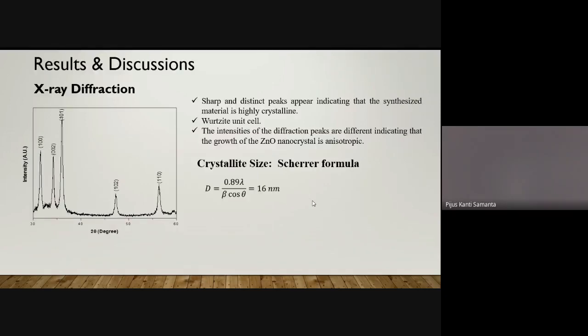The structural studies involved X-ray diffraction studies, and here it shows the X-ray diffraction pattern of the synthesized material. Sharp peaks appeared over here that indicate the good crystallinity of the material, and we have indexed these peaks and found the structure to be hexagonal, and this peak indexing is quite consistent with the standard JCPDS. And from the diffraction curve, we can also calculate the crystallite size. In fact, by crystallite size, we mean here the coherent domain participating in diffraction of X-rays.